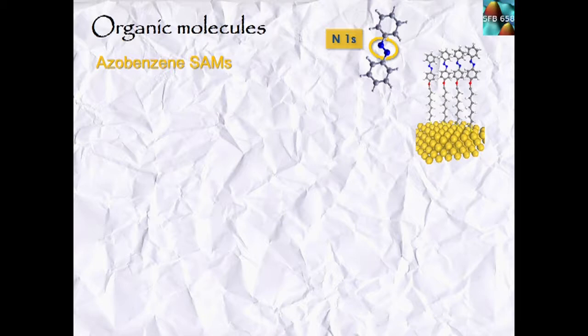Because, as you see, they form very nice self-assembled monolayers, so very nicely crystalline packed structures. And this may be another reason why they don't switch anymore, because they start to talk to each other when they are excited. If they're close to each other, due to this packing, they don't have the same excitation properties anymore like the bare molecule. And this is what I would like to show you.